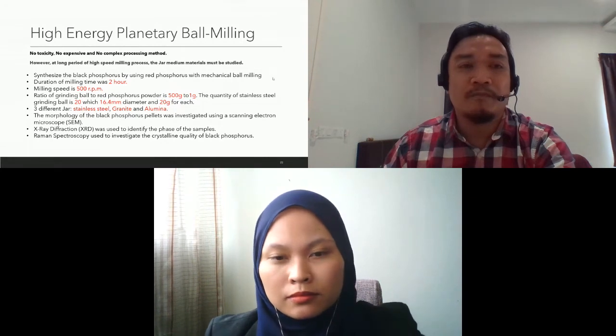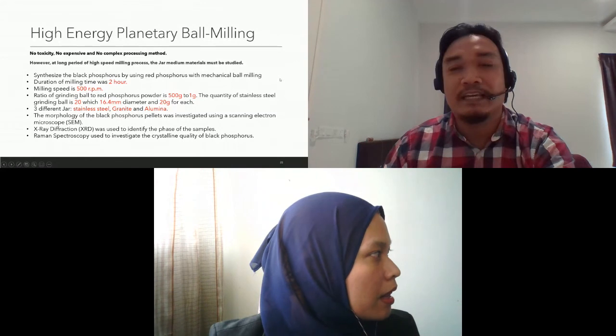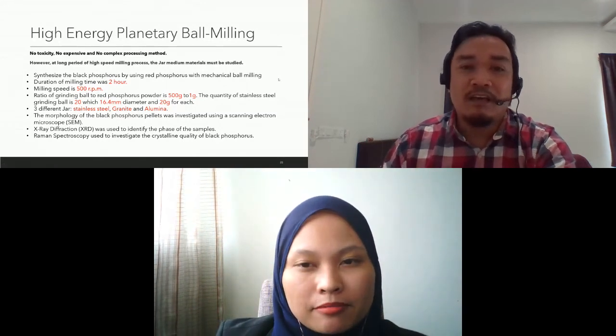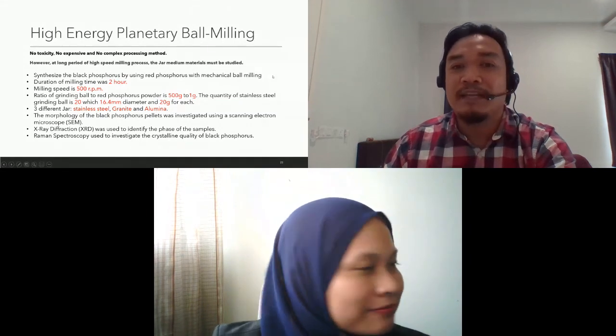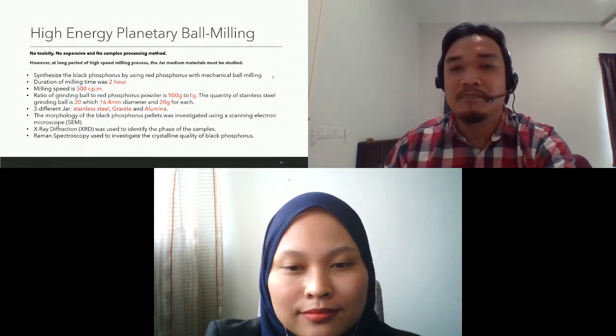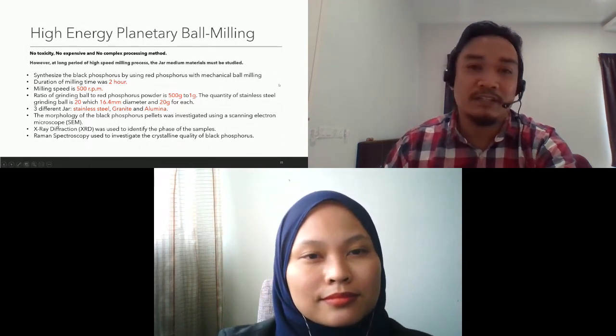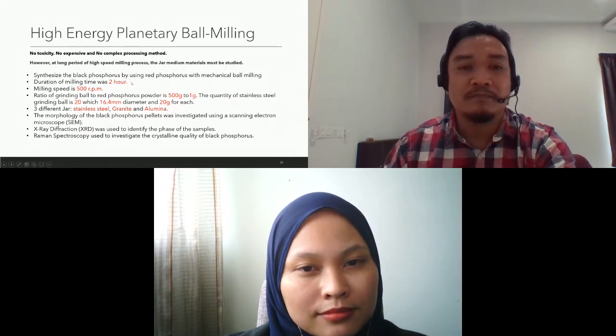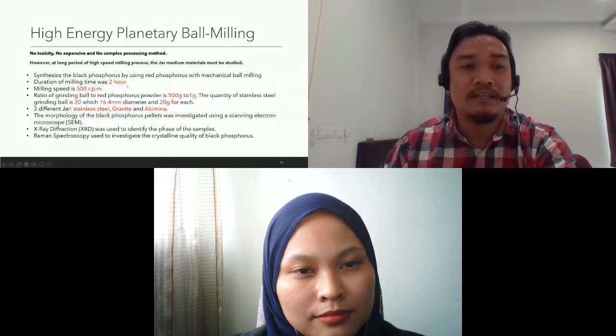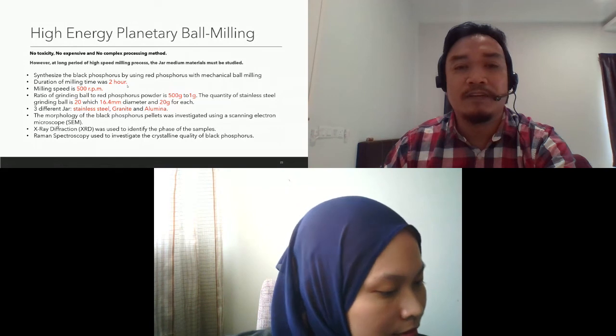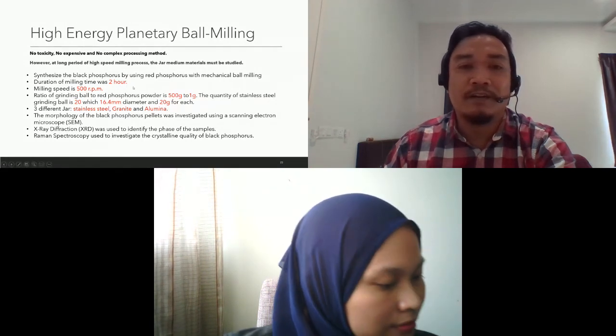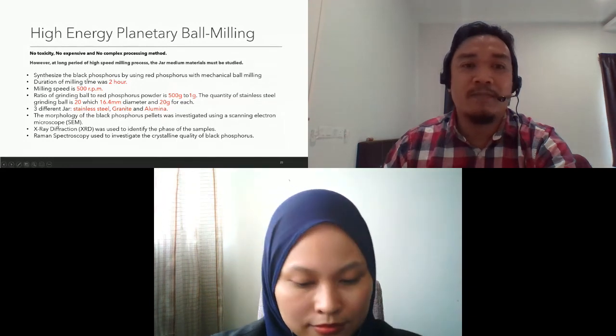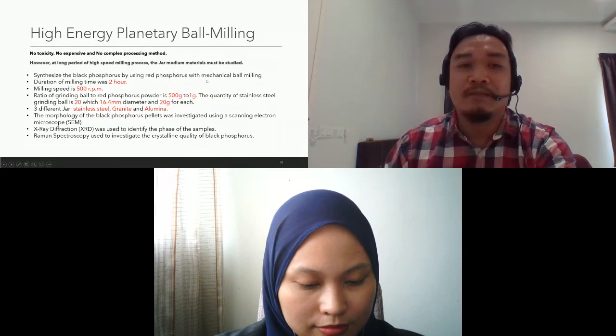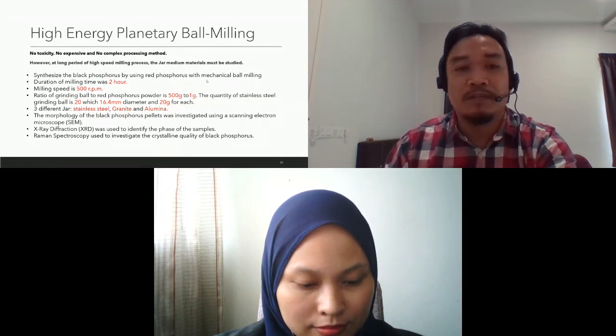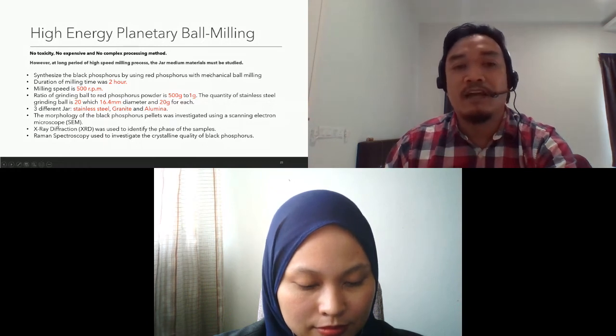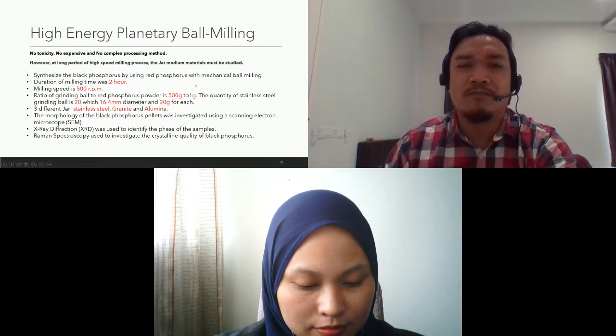we have produced BP by using high energy planetary ball milling. We call it the ball milling process. But at a long period of high speed milling, the jar or the medium that contains the RP must be studied. So in my research, we will study the effect of using different kinds of jar materials. We will synthesize the black P by using RP with mechanical ball milling. The duration of milling time will be 2 hours, and the milling speed is around 500 RPM, which is a very high speed of ball milling.